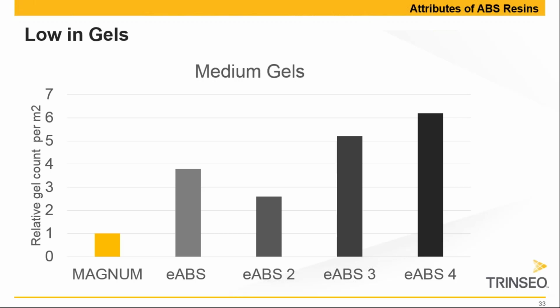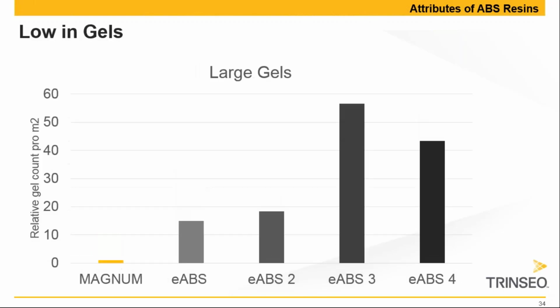If we move now to the large gels, the difference is even more dramatic. We are looking at a factor 10 more, even 50 more in presence of large gels for some emulsion ABSs versus Magnum. That means if you are in critical extrusion thermoforming applications, it is wiser to use Magnum ABS versus one of those emulsion ABSs.